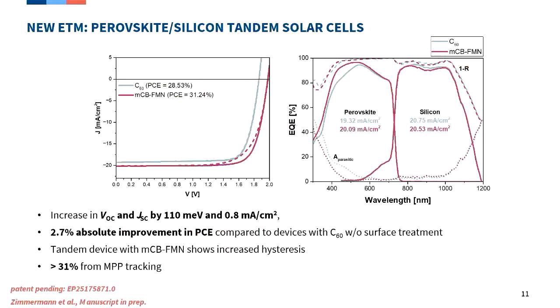So as I said, we put it in tandem solar cells - here are the results. First let's look at the right plot, the EQE. Especially in this wavelength region, you see higher EQE for the new molecule compared to C60, because of less absorption. That amounts to about 0.8 milliamps per square centimeter, which is quite a lot for a tandem solar cell.